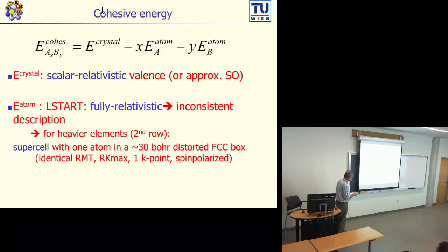That means we generate a big cell with a lattice parameter of about 30 Bohr. It is best if you select a face-centered box but distorted. That means make A, B and C slightly different, something like 30, 30.1 and 30.2 Bohr or so, so that it breaks symmetry. That means Px, Py, Pz are not forced by symmetry to be equal, and this allows you then a full